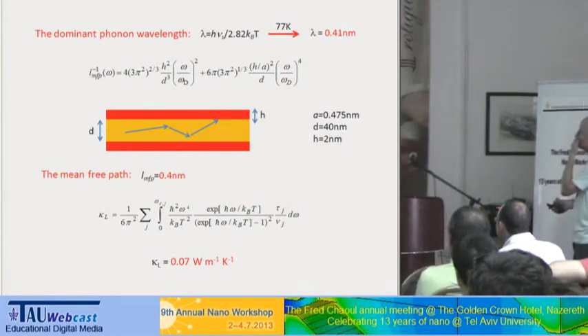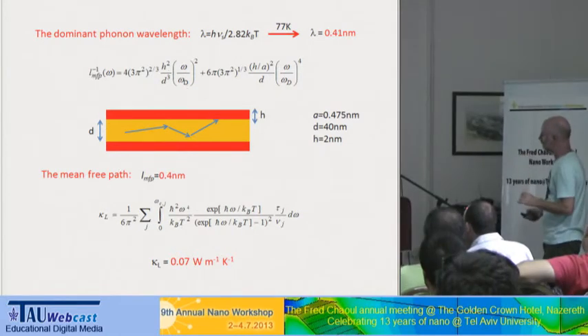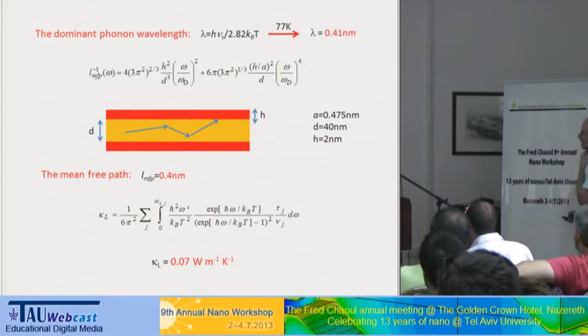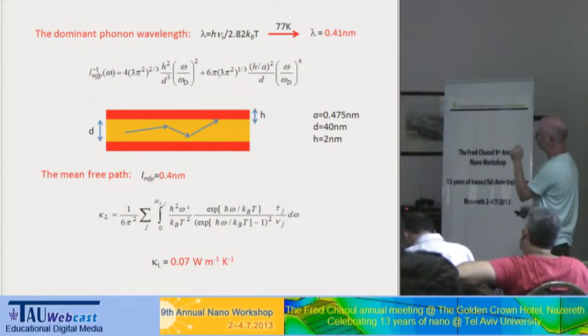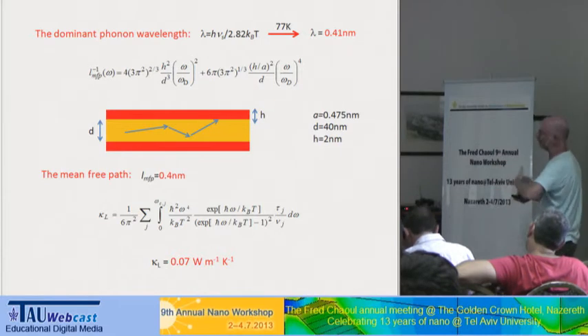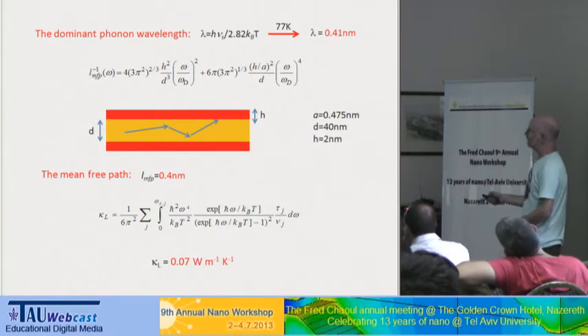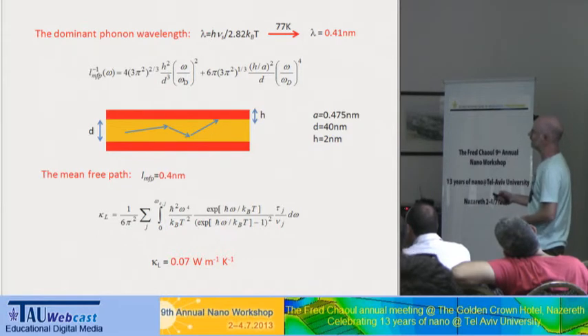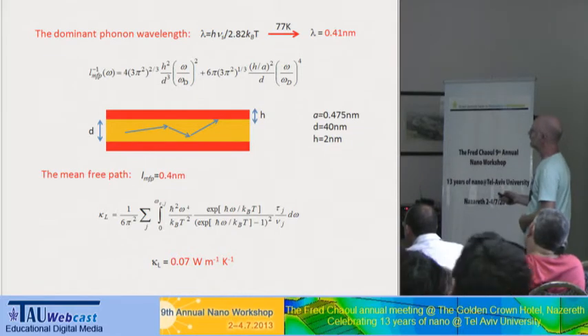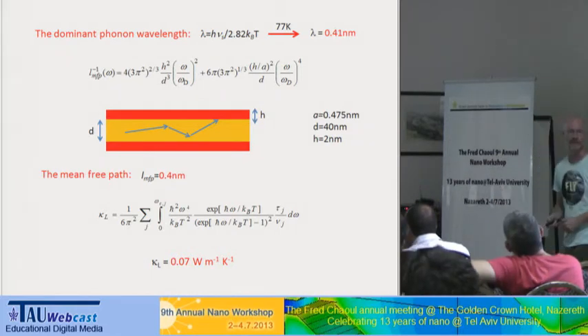I won't go into this. The idea is the following. If you want to calculate the thermal conductivity by the equation, you need to make sure that what you are measuring is an amorphous solid. The dominant phonon wavelength in Bismuth, given the velocity of sound inside the Bismuth, is 0.4 nanometers.